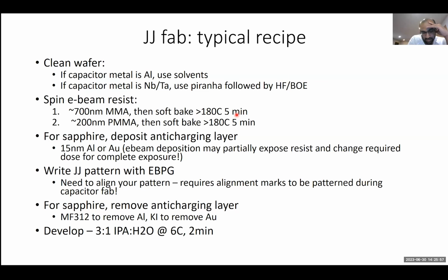Let me think. Personally, with the junctions that I've made, I haven't noticed a lot of aging. The most aging I've seen is after like 9 months, the resistance is increased by 1 kilo ohm. But within like a week, that's like 10%. Okay, maybe no, like 15%. But within a week, I haven't noticed any sort of aging.